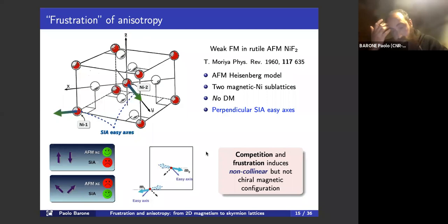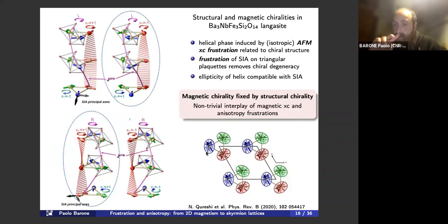Now, one may wonder if it's possible to have instead a removal of chiral degeneracy with this kind of mechanism. And I would say that yes, this is possible. That depends on some particular cases. So here I show the expected, well, at least the modeled magnetic phase of a rather complicated system, which is this oxide with a langasite structure.